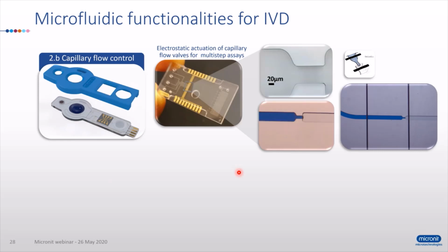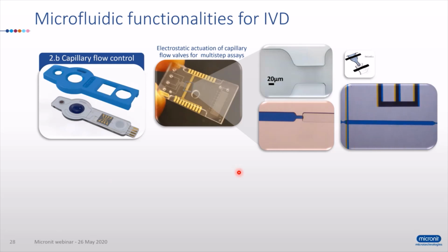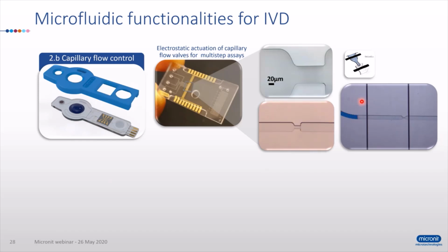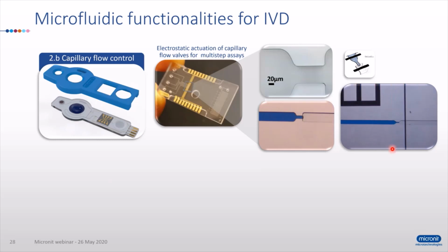Of course, if we want to perform a multi-step assay, like the workflows that we have seen in previous slides, we also need to add a time component. So once the flow stops at the valve, we should be able, at the right time, to re-trigger the flow. And this can be done by electrostatic triggering. So by patterning thin films of metals, so metal electrodes before and after the valve, and when applying a short pulse of voltage across these electrodes, that will trigger the flow to continue. In this way, we can add the time component.